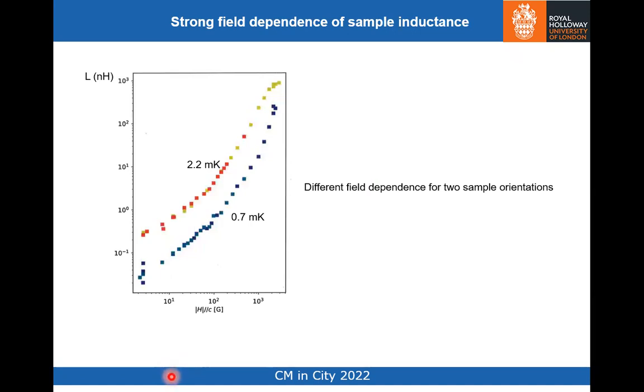So the piece of experimental evidence here is that we need to tension this data with those three ideas, but I wanted to be upfront about what it is that we actually see with magnetic field. This is fields applied along the z-axis. We see this huge variation in the sample inductance, and the sample inductance has different field dependencies for two sample orientations, and we don't really fully understand that. But since this is show and tell of experimental data, I want to show that.